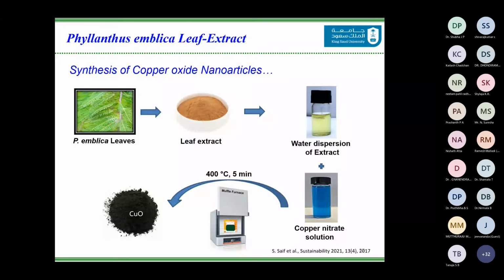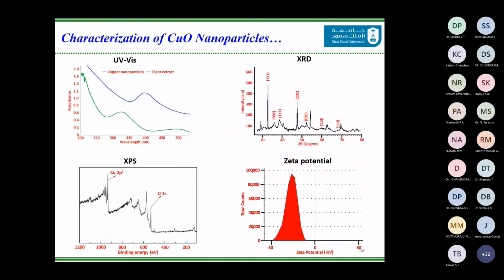So the copper oxide nanoparticles, you can see they have a lambda max which is very much different than the plant extract. And as observed, the crystalline nature of the copper oxide nanoparticles was confirmed by XRD. However, there was another set of diffraction patterns that were obtained, which could be due to the presence of phytomolecules or some inorganic impurities in the plant extract. The XPS analysis revealed the presence of copper and oxygen in the desired oxidation state.